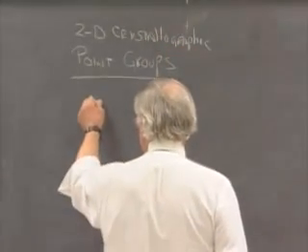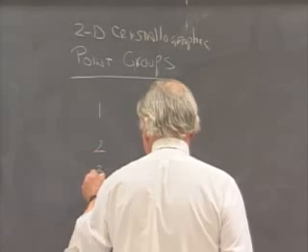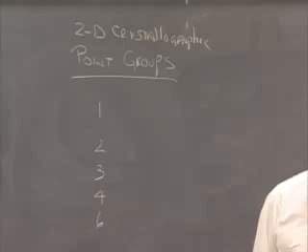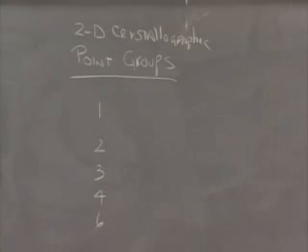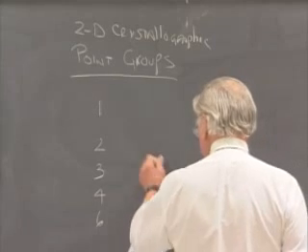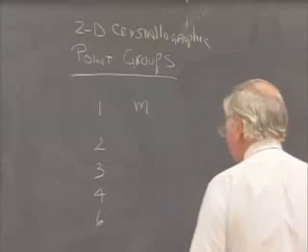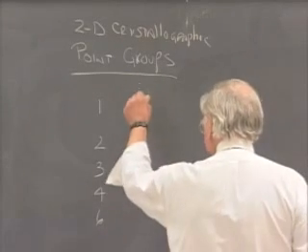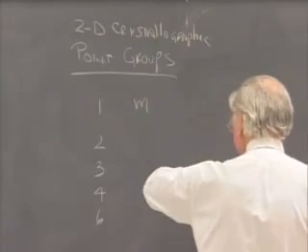We had rotation axes by themselves: 1, 2, 3, 4, and 6. These are the only ones we need worry about because these are the only rotational symmetries that are compatible with translation. Then we had a mirror plane. And then there was no reason why we could not combine a mirror plane with these rotational symmetries.